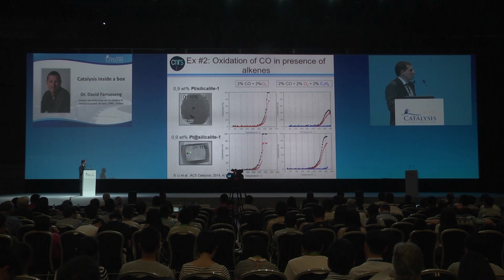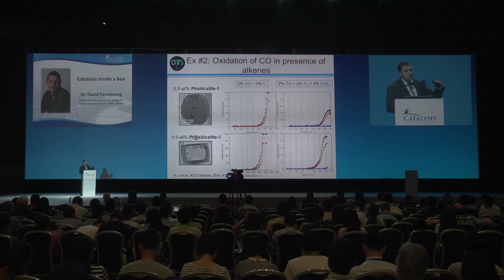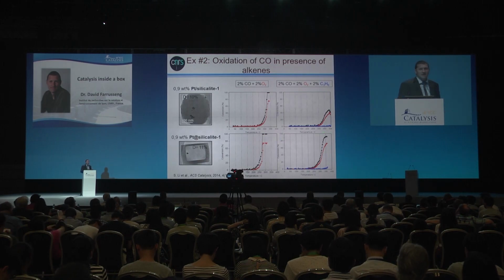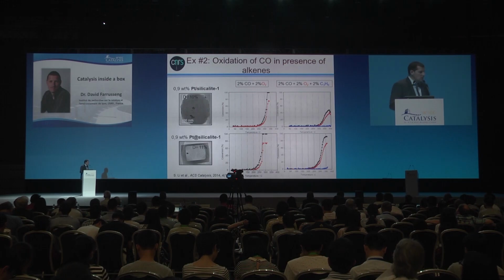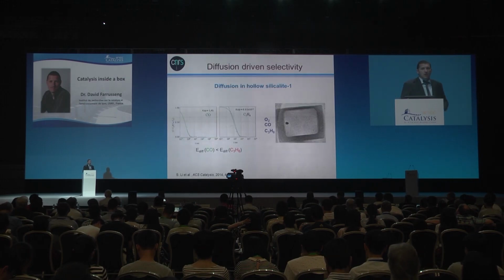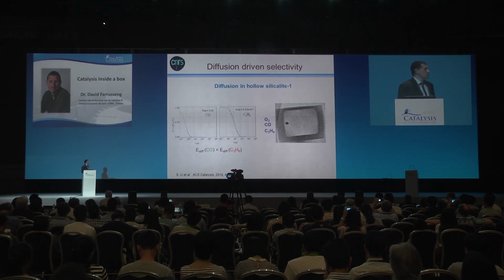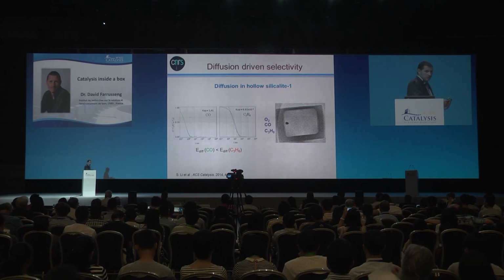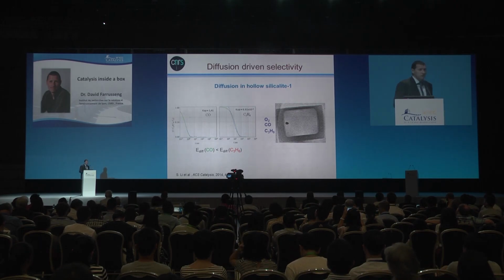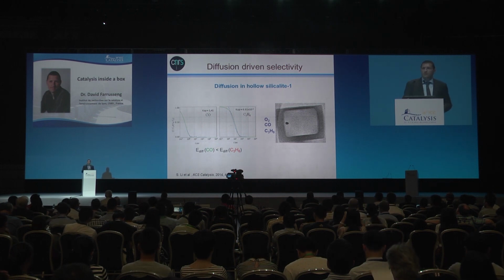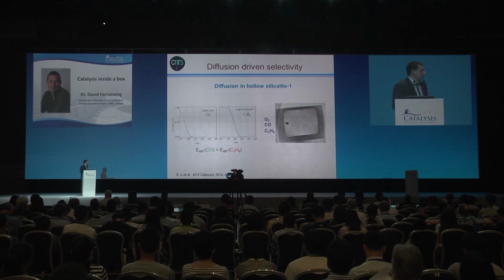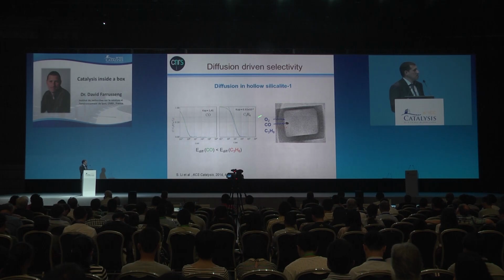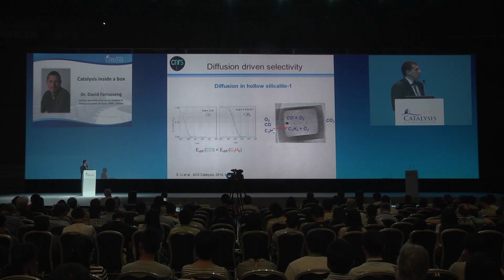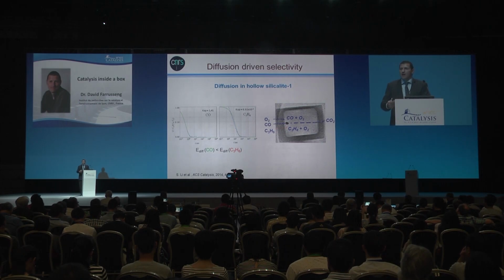In contrast, in our case, you see a slight decrease of the CO conversion, but still reaching more than 90% conversion. And what we believe is that this is because we have diffusion limitations in the case of the propylene oxidation. We have measured both the CO diffusion rate and the propylene diffusion, and we found that there is a difference of, let's say, 2 orders of magnitude in the diffusion kinetics. So it means that very likely the CO and oxygen cross the membranes very fast and react, whereas the propylene slowly diffuses through the catalytic particles and then reacts with much less apparent kinetics, so to say.